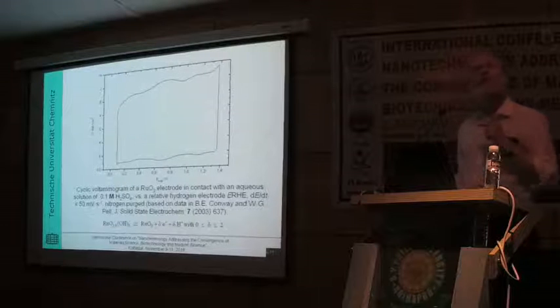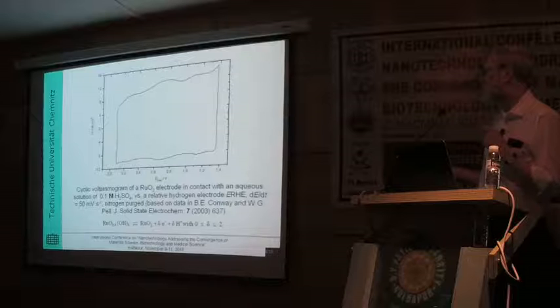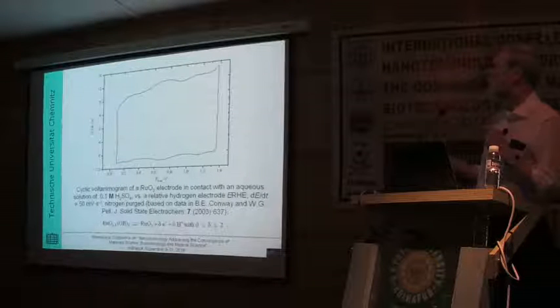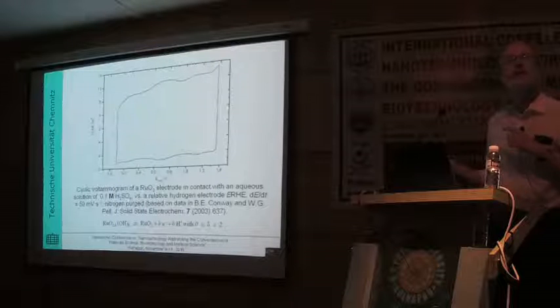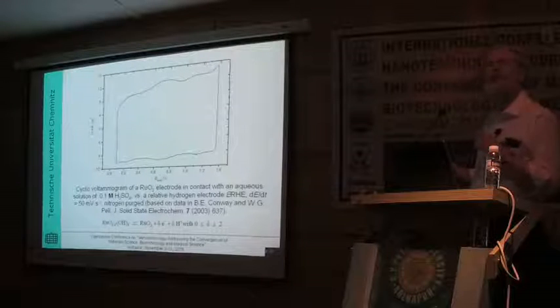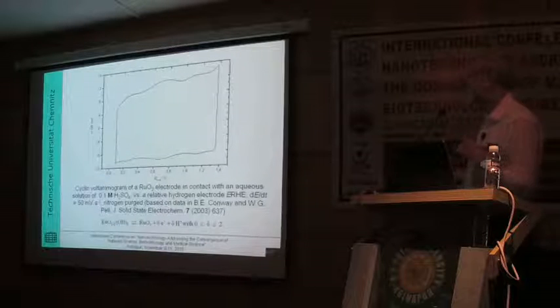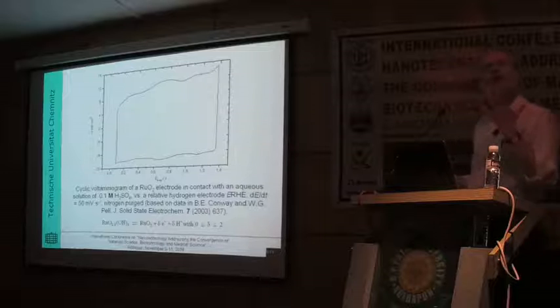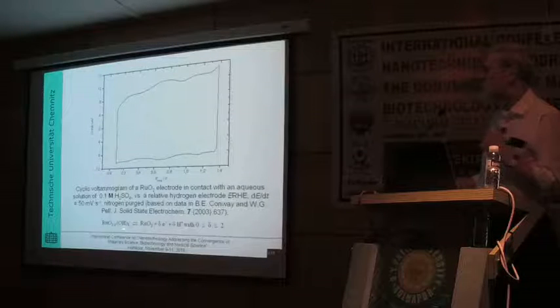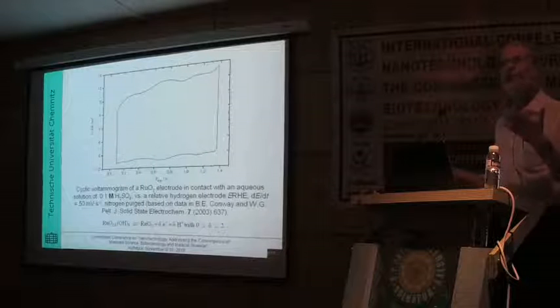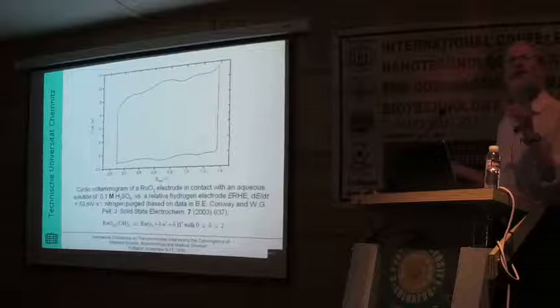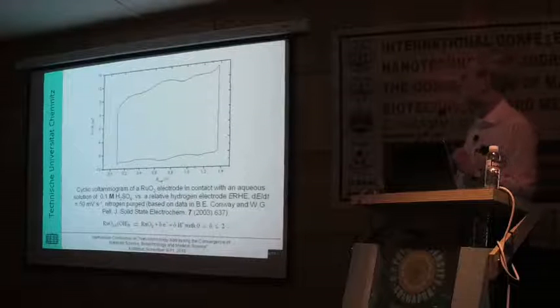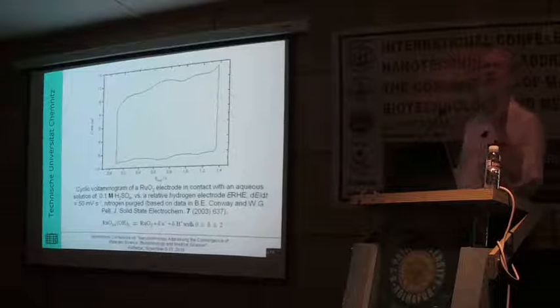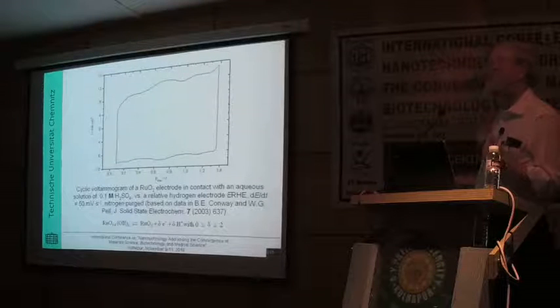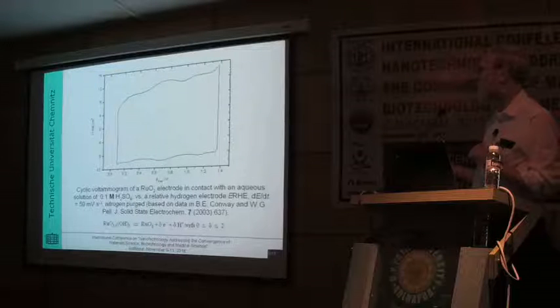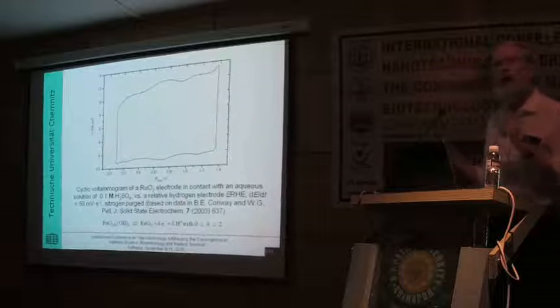Well, this is a very early example reported by Brian Conway and W. Pell. It's the ruthenium oxide. And once again, you see not exactly a rectangle, but you see an almost rectangular response and very weak waves on it. The assignment, the interpretation, what is going on, has been given by Conway. It's the change of the redox state of oxidation of the ruthenium, and the ruthenium has various states of oxidation, so the electrochemistry is a little bit more complicated, and these waves, I would not call it a peak, these waves are somehow associated with ruthenium 3, 4, 5, 6, and so on. But why is there such a huge current under these very weak waves?